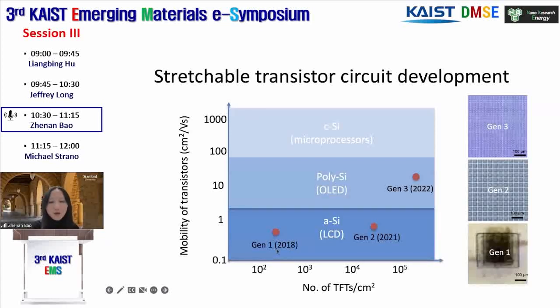So for the first generation of stretchable integrated circuits, they were fabricated using photoresist and etching patterning, as well as combined with some shadow mask. So the transistor density was only 300 transistors per centimeter square, and the mobility was in the amorphous silicon range. Second generation, we were able to develop the materials to be directly photo patternable and still maintain the mobility of amorphous silicon, but much increase the density of transistors.